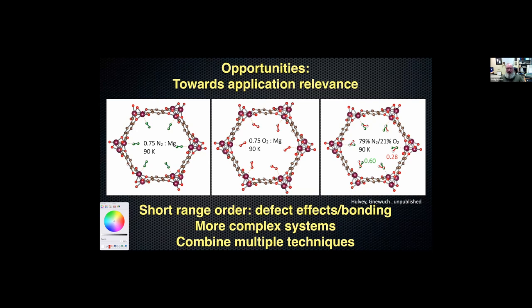And here's an example that we haven't published yet, and that's looking at competitive absorption. Of course, it can't be competitive absorption for molecules that give you the same molecular structure through the diffraction process. But here we have oxygen and nitrogen binding in a metal organic framework, and they're slightly different. And so you can be quantitative. Of course, there's a difficulty going away from the 90K measurements here towards room temperature, where things become more disordered, and then it might become impractical.